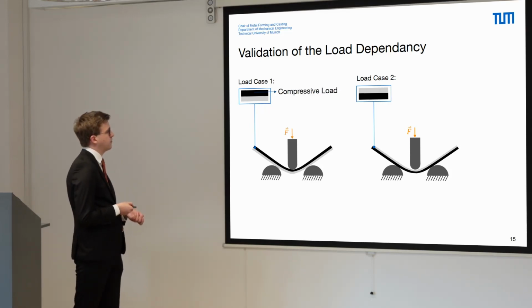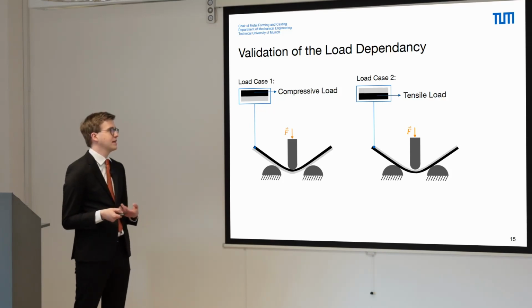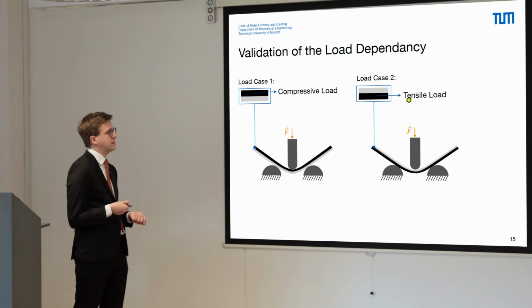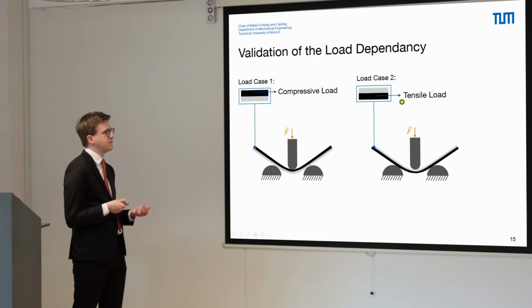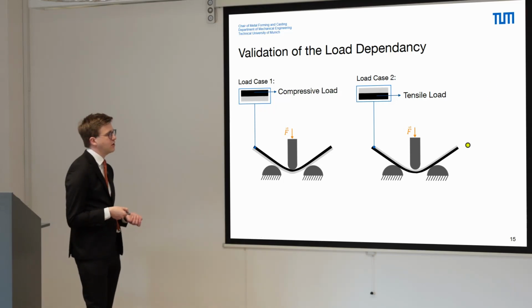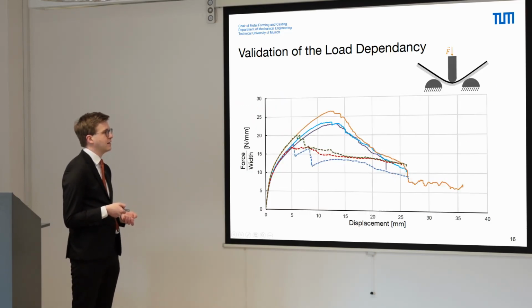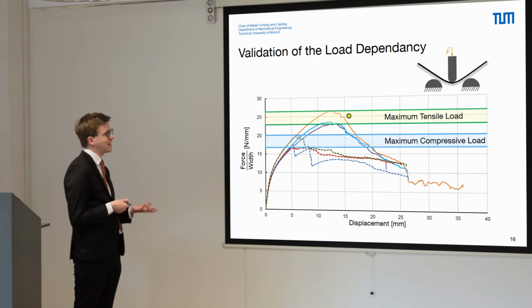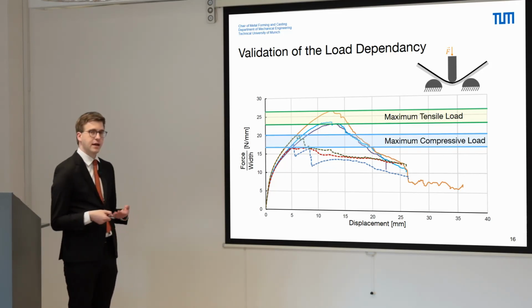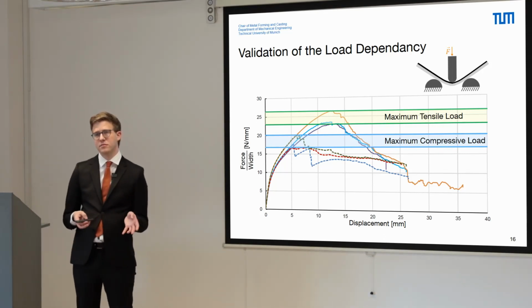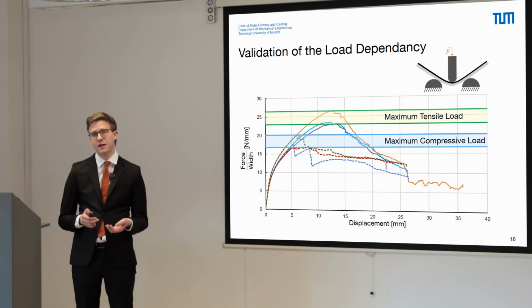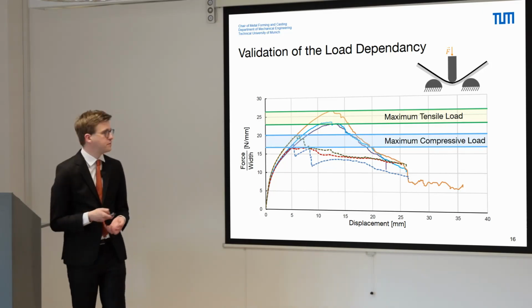In the first configuration, the UD fibers are subjected to a compressive load due to the upper position in the experiment, and in the second configuration we subjected the fibers to a tensile load since they are now in the lower position. The results show that the maximum tensile load is significantly higher than the maximum compressive load for these three samples. This can be explained with phenomena such as micro-buckling of the fibers under compressive load.